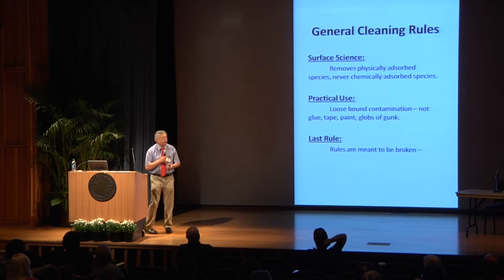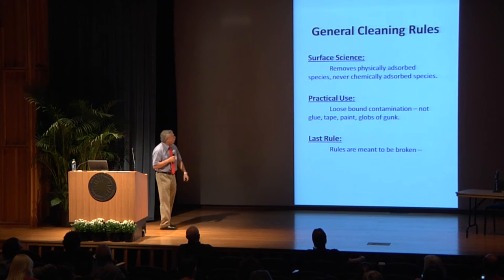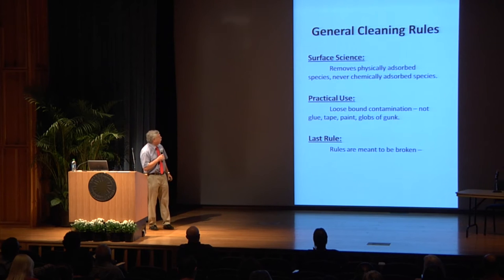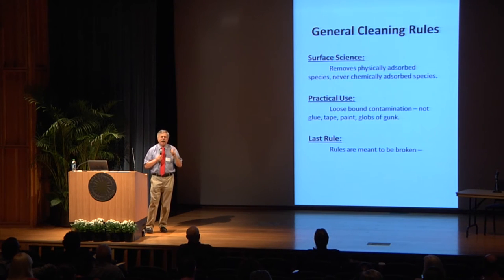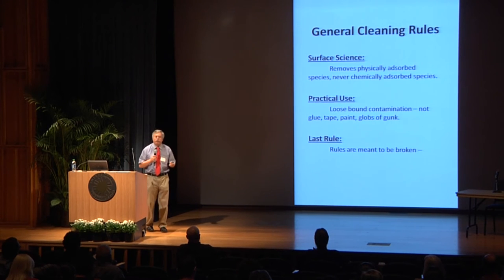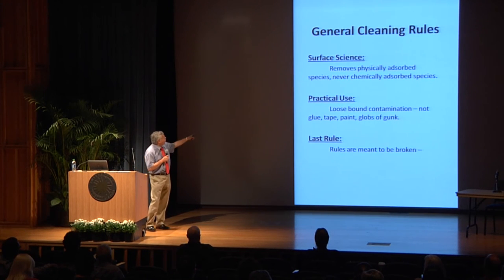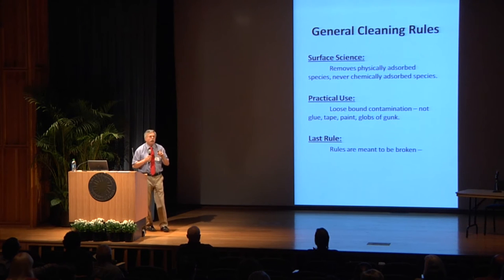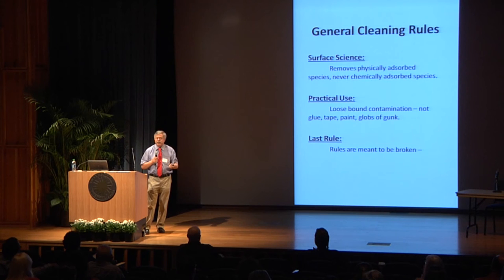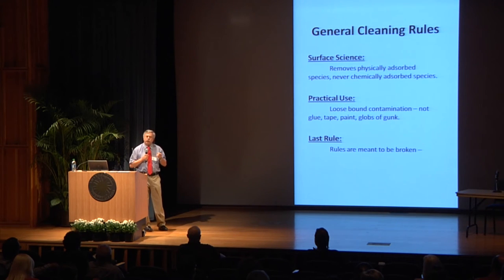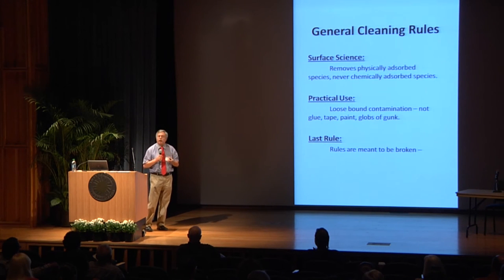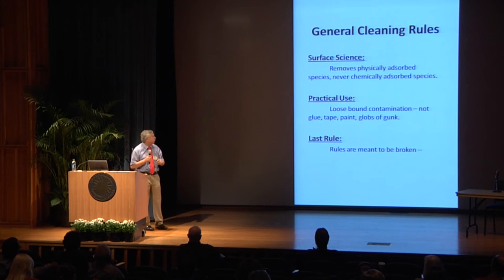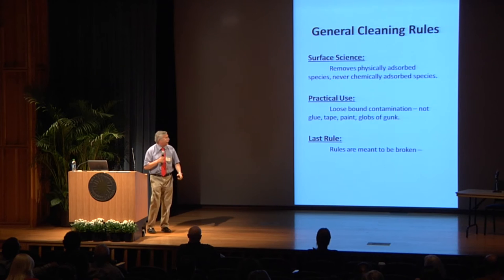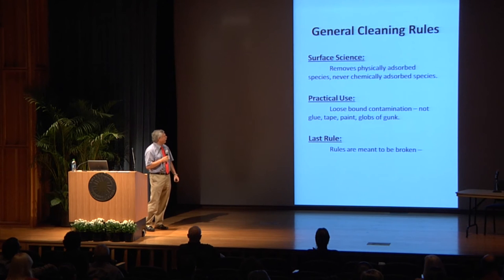So I want to talk about the basic rules of surface cleaning. From a surface science viewpoint, it removes what's physically adsorbed. By physically adsorbed, we're talking about things bound by van der Waals forces, electrostatic, capillary forces, essentially weak. Never chemically adsorbed species. By that, I mean covalent bound, ionic, metallic bonding. They stay. This implies that essentially a material should not be abraded. And there's only one or two materials that can be abraded because of their structure, but it's extremely limited. Practically, loosely bound contamination can be removed. Not glue, tape, paint, globs of gunk.